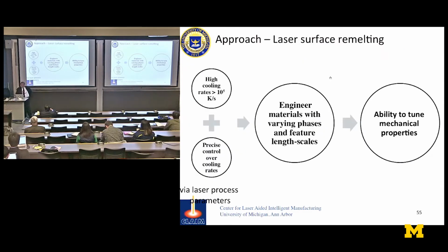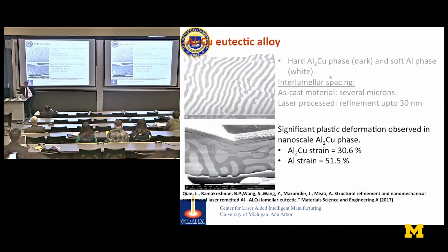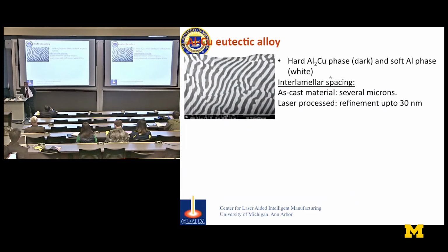So what we started looking at is how we can get the high cooling rate, which is natural with laser, precise control over the cooling rates, engineer the materials with varying phases and features, and the ability to tune the mechanical properties using laser treatment. Okay? So this is the aluminum copper system. This is the eutectic we got.